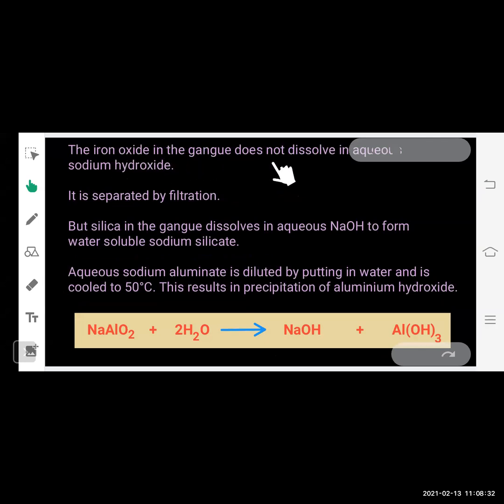The iron oxide in the gangue does not dissolve in aqueous sodium hydroxide, and it is separated by filtration. But silica in the gangue dissolves in aqueous sodium hydroxide to form water soluble sodium silicate. Aqueous sodium aluminate is diluted by putting in water and is cooled at 50 degrees Celsius. This results in precipitation of aluminium hydroxide. You can see sodium aluminate is diluted by putting water in it, and it is cooled at 50 degrees Celsius. And as a result, we are getting aluminium hydroxide and sodium hydroxide.